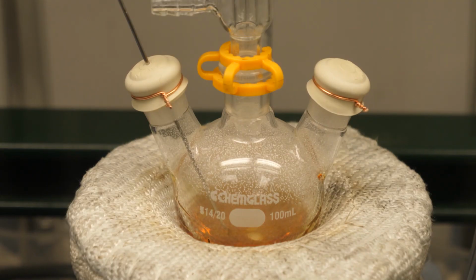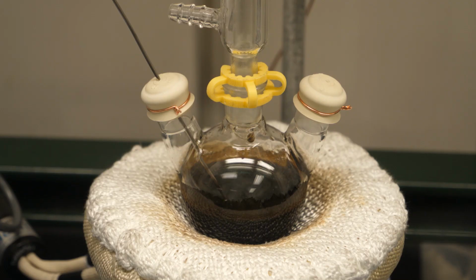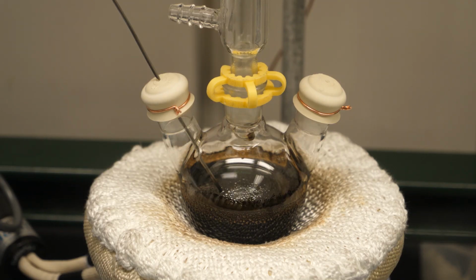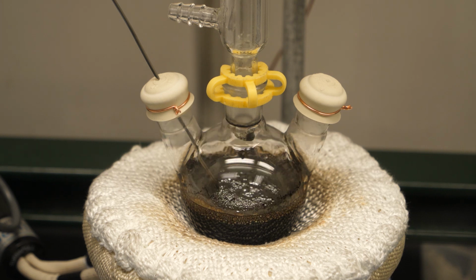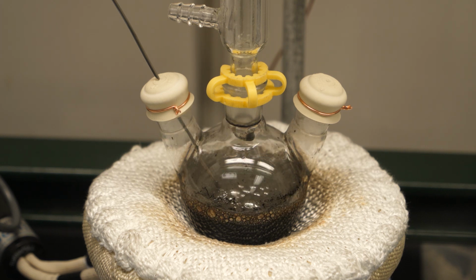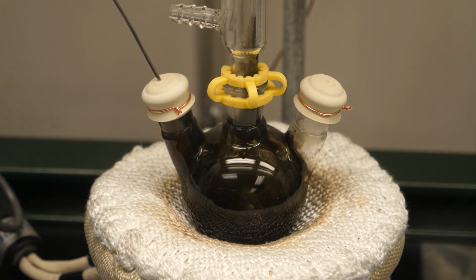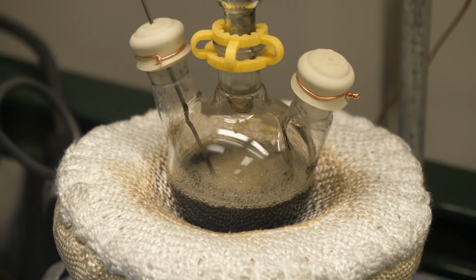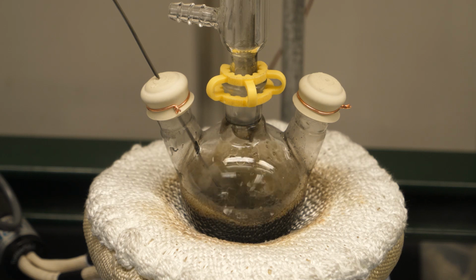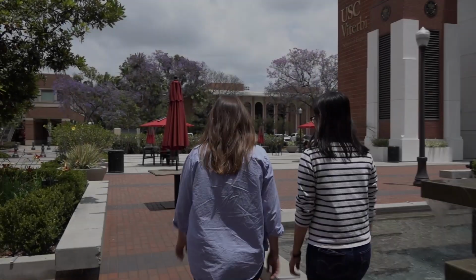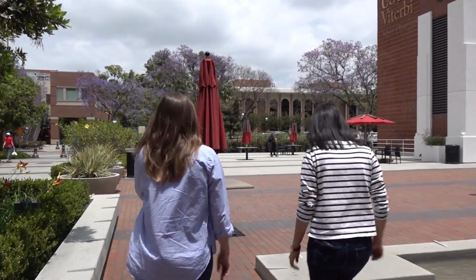During the synthesis of metal carbide nanoparticles, the molecular precursors can undergo sublimation. At the same time, volatile byproducts are being produced that can explosively vaporize. Additionally, the key features of the nanoparticles that we are trying to control are highly sensitive to thermal and chemical inhomogeneities. These inhomogeneities can arise due to the increased solvent volume and changes in heating rate when transitioning to larger scales. Addressing these challenges really requires us to look at alternative approaches for producing large quantities of nanoparticles with the critical properties that have been demonstrated and refined during the catalyst development cycle.